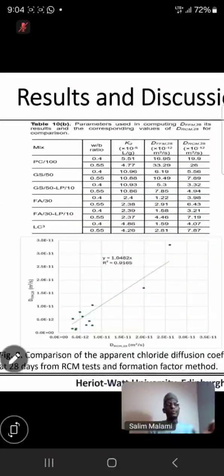So then after we use this, we go to diffusion modeling again. Apparent diffusion coefficient, chloride. In concrete, when salt passes through the concrete, there is binding chloride and free chloride. When chloride or water with salt passes through the concrete, some amount is chemically or physically attached to the concrete. That attached one we call binding chloride. It has no effect because it is not free to go to the reinforcement, that is the steel bar, and cause corrosion. So we call it bonded